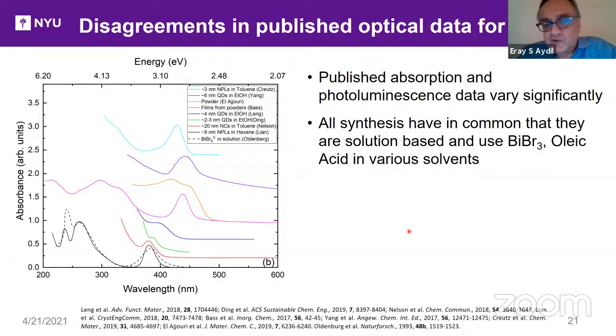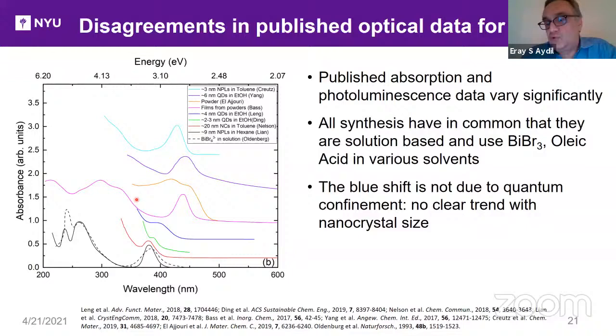And if you look at this here, this absorption data is presumably coming from the same material. Your first impression might be, well, there are nanocrystals and there are dispersions, so maybe there are quantum confinement effects that are shifting the absorption to the blue direction, okay? I can tell you that the blue shift is not due to quantum confinement because there's no clear trend with nanocrystal size. I will give you an example. Here is this one at around 440, and it's from 3 nanometer nanocrystals. And here's one that's larger, 20 nanometers, but it's blue shifted. So if it was indeed quantum confinement, these two should have been reversed.